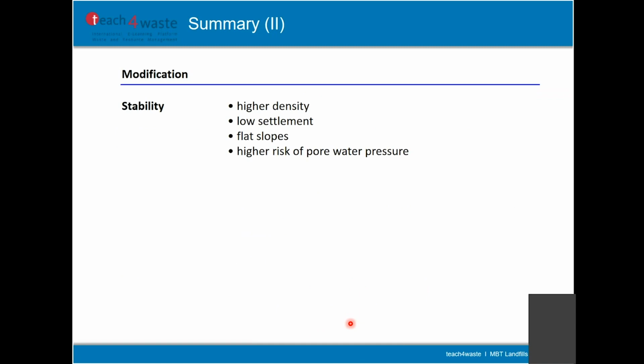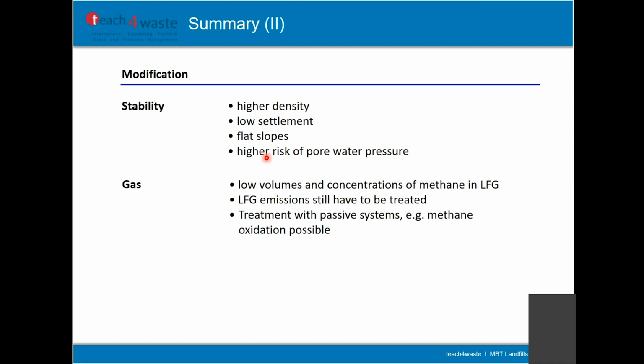Then, in view of stability, we have this higher density of the material, we have low settlement compared to fresh waste, but we have these flat slopes we have to take care of, and also this higher risk of pore water pressure, which might occur inside of the landfill and which reduces the stability of the landfill. In view of the gas, we have low volumes and concentration of methane in landfill gas. We still have to treat this low emission rate, these low fluxes, but we can use this very simple passive system, which has low invest costs, but also low costs during operation.